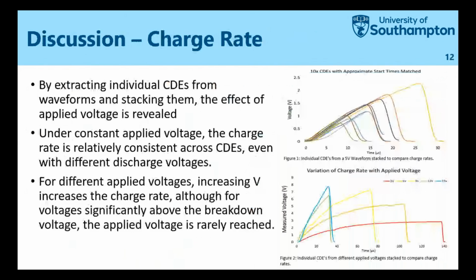So what can I do with these waveforms? To start off with, I've just extracted individual discharge events and stacked them together. The first one was for the 30 kilo ohm resistor from test 1. I put ones under the same voltage just to check that the charge rate was similar, and it shows that they are, which means the film thickness is constant, or as consistent as it needs to be for this sort of test.